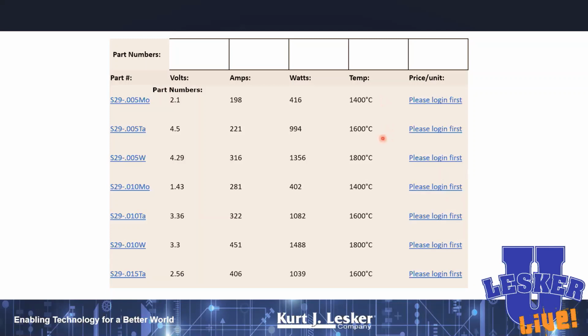Here's a 5/1000th of an inch thick tantalum boat, 1600 C, kind of too close. I wouldn't really use that one. If we drop down one more though, this 5/1000th of an inch thick tungsten boat, if my power supply can give me 4.3 volts and 316 amps, that boat will go to 1800 C. So that's well over where I need to be in terms of the 1550 I'm trying to generate. So that's probably a decent choice to do aluminum oxide.